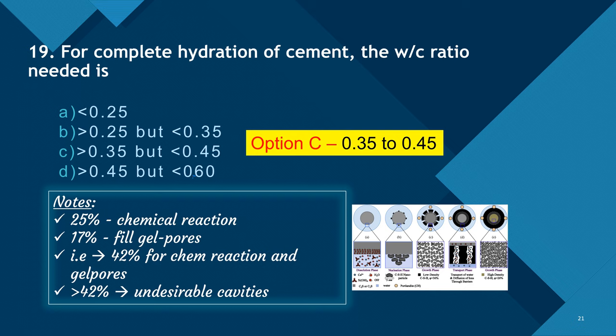So a certain quantity of water is imbibed within the gel pores. That water we will call gel water. Adding these two, 25 plus 17, we will get 42%. So 42% of water by weight of cement we add will be used for chemical reaction and gel pores only. So what if we provide more than 42% of water? On an average, more than 42% of water by weight of cement is undesirable, because it will produce undesirable cavities and holes between the cement particles that will inhibit the activities of the Bogue compounds.